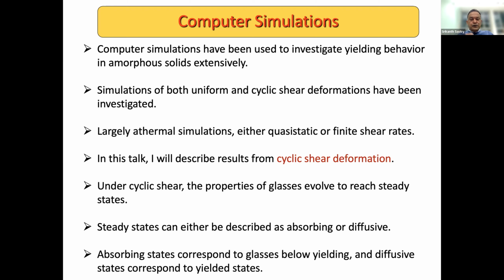Broadly, there are two regimes to this steady state behavior. In the first regime, after some number of cycles, during which there is plasticity and rearrangement and reorganization of configurations of atoms or molecules, you reach a state which doesn't change anymore from cycle to cycle. So you go through a limit cycle, and these are called absorbing states. The other behavior is described as diffusive: looking stroboscopically, cycle by cycle, at where the particle positions are, these positions evolve in a diffusive manner. Okay, so absorbing states correspond to glasses below yielding, and diffusive states correspond to yielded states.